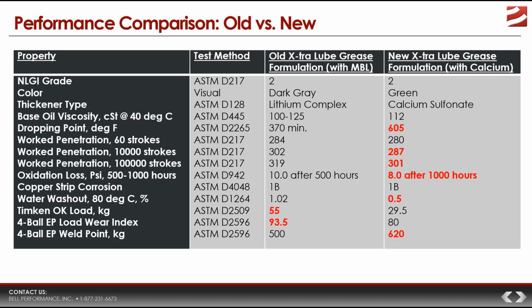The new X-tra Lube Grease has a dropping point that's more than 100 degrees above the old formulation, 605 degrees Fahrenheit. And so that means that the operating temperature limit for the new grease is also 100 degrees higher, and that is a significant difference.